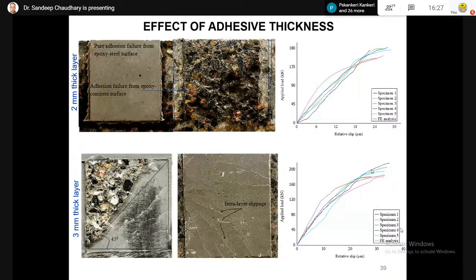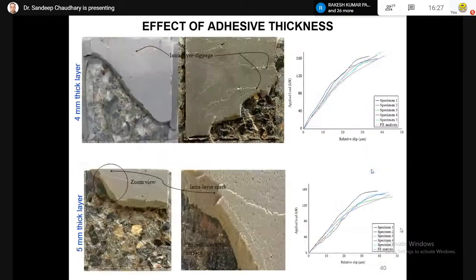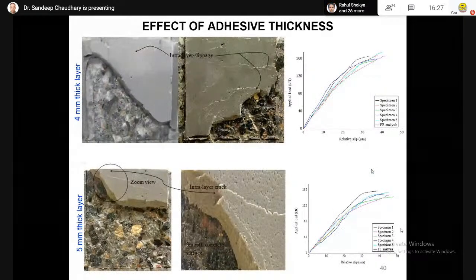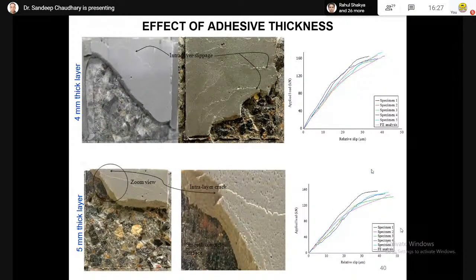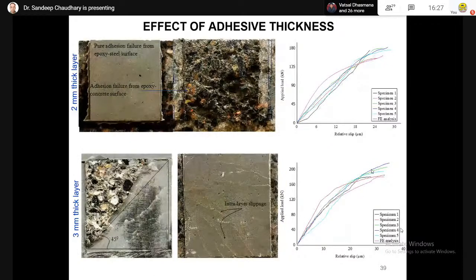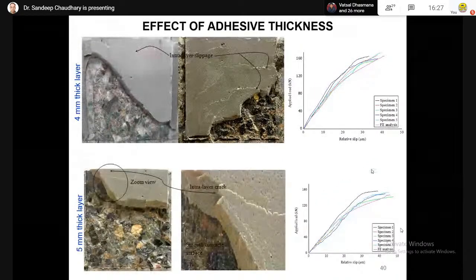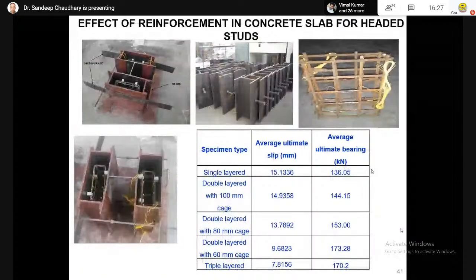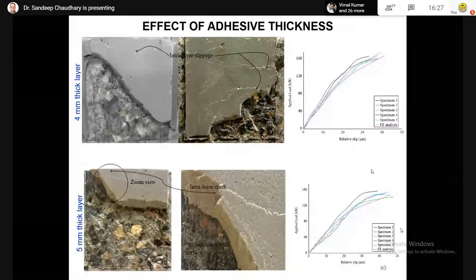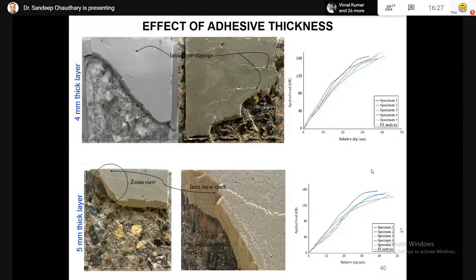So it is changing from adhesion failure to intra-layer slippage when we are moving from 2 mm to 3 mm thick layer. And when we moved to 4 mm thick layer, these intra-layer slippages were again predominant. When we further increased the thickness of epoxy layer to 5 mm, there were intra-layer cracks which were observed. So the behavior is changing from pure adhesion failure to intra-layer slippage to predominant intra-layer slippage to intra-layer cracks. So that also tells that it's important to define an optimum thickness of epoxy for bonding of steel and